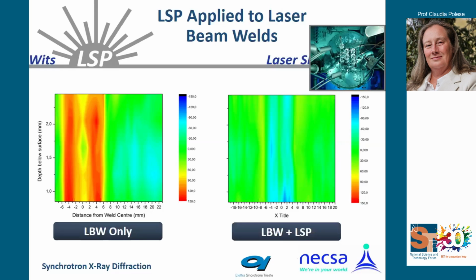These are complex matters involving X-ray diffraction and neutron diffraction, but basically the picture on your left shows a lot of red. And in my field, red is a bad thing. It means that you have some damaging stresses. After applying laser shock peening, as you see on your right, we revert the situation to a full blue-green situation, which is very good.